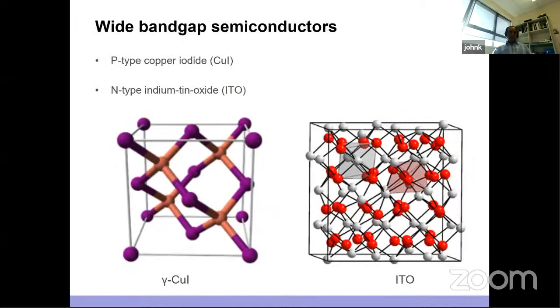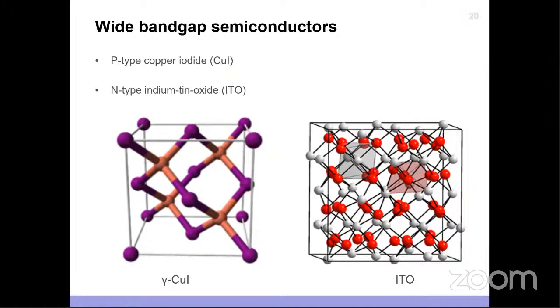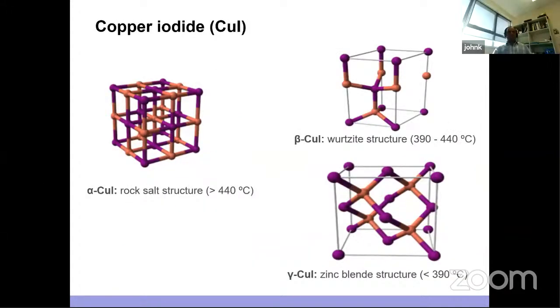So copper iodide, to start with. As I said, we are going to present copper iodide and indium tin oxide. So let's take copper iodide. It has 3 phases: a rock salt crystal structure, a wurtzite structure, and a zinc blende structure. It's a p-type transparent thermoelectric material, with a band gap of around 3.1. The crystal structure is almost polymeric, as I said before, and it's predicted to have a figure of merit of 0.2 at room temperature and a high Seebeck coefficient around 200 microvolt per Kelvin. So it does have good properties at room temperature, and it has to be in the gamma phase. As a zinc blende structure, it can have high transmission and Seebeck coefficient.